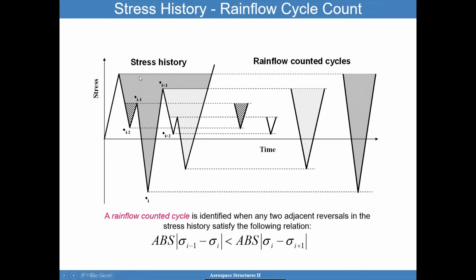As you can see here, this Rainflow count can be counted as a cycle because that corresponds to the largest range that I have from this point to this point. And so that one really counts. Then the next one that's big is the one that goes from here to here. So that counts. And then I have the smaller triangles that should be counted. But I don't want to start counting there. I want to start counting from the big ones to the small ones. And that's really the way you want to go about it.